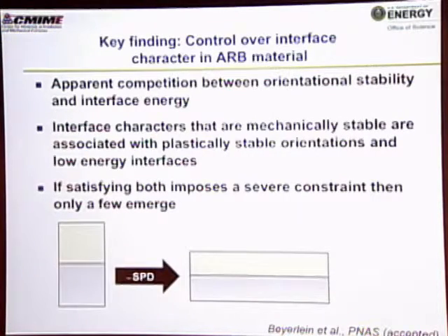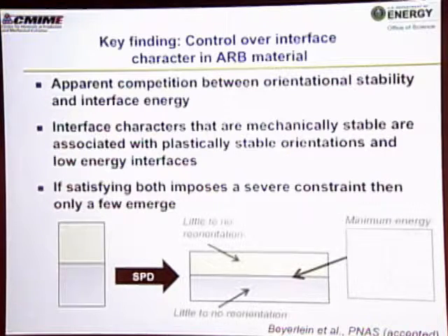It means that when you roll this material out, you have to have these crystals not reorient as you roll them, and they have to have a minimum energy. You don't want a highly energetic interface that would form during this process. So if you satisfy both these conditions, then you should only get a few interfaces. And the fact is that's exactly what we see. And these are the types of interfaces that we're going to talk about with the rest of the talk today.